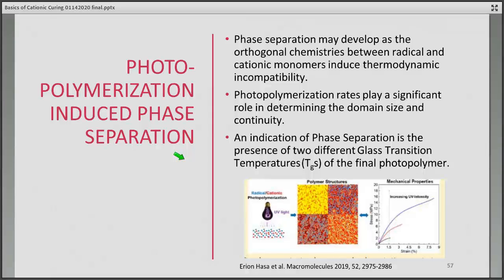And instead of forming your IPN, your tangled web, or a ball of yarn, you actually get phase separation. This develops as the different, or orthogonal, chemistries between radical and cationic monomers react and induce thermodynamic incompatibility. So they basically push away from each other and form domains. Photopolymerization rates play a significant role in determining domain size and continuity. An indication of phase separation is the presence of different glass transition temperatures in the final photopolymer.